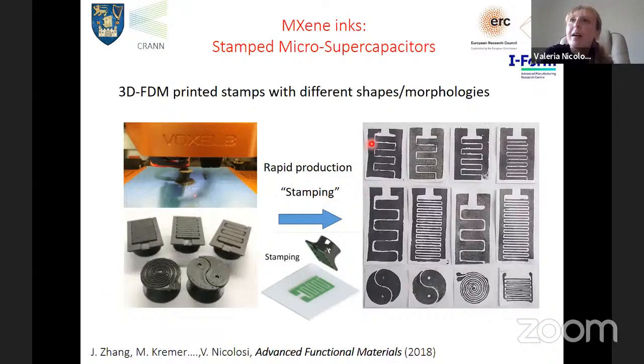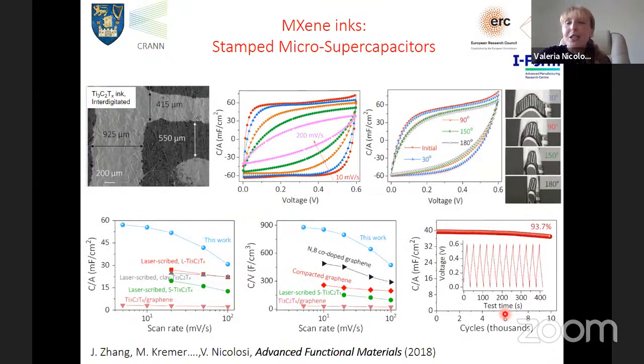So here, for example, are real devices that we stamped on paper. And these devices do indeed work. This is the proof. Here is the device on paper. Here are the printed paths, here are the stamped paths, and here is where there was no ink. And indeed, here we pushed the device up to 200 millivolts per second. You start getting some resistive behavior here, but at lower scan rates, you really get a fast response and a lot of capacity. And the wonderful thing is that these devices are fully bendable. Here we bent them up to 180 degrees and the performance is not changing at all.